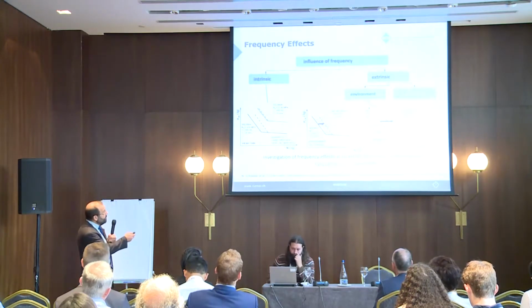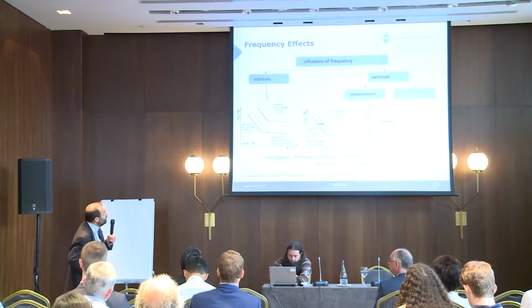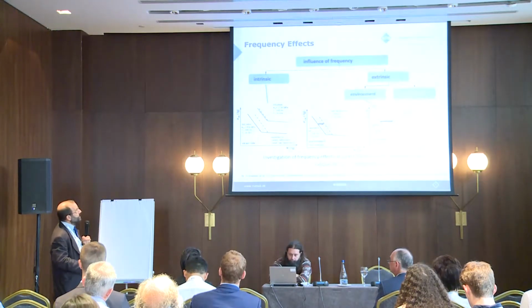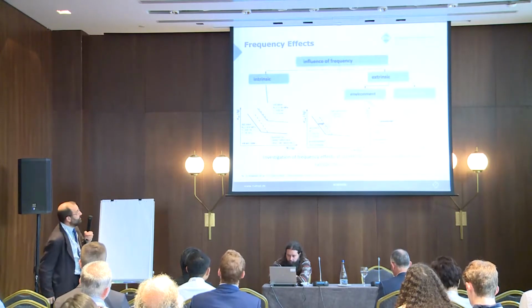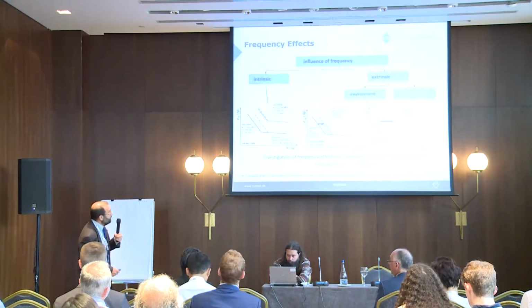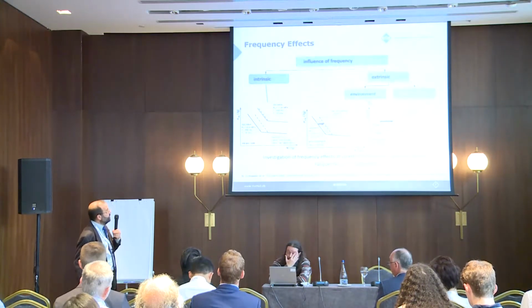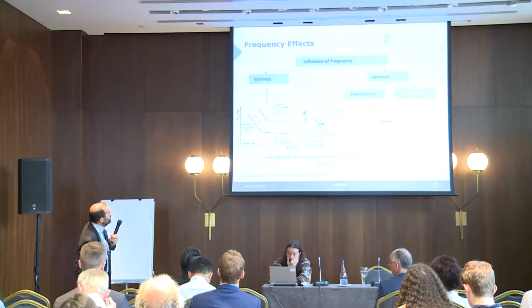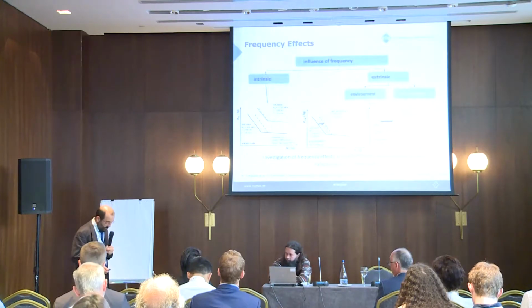And for an aluminium alloy that he tested, he could find almost no effects when testing in inert atmosphere, but a big effect in air. So he could conclude that this must be related to environmental effects.